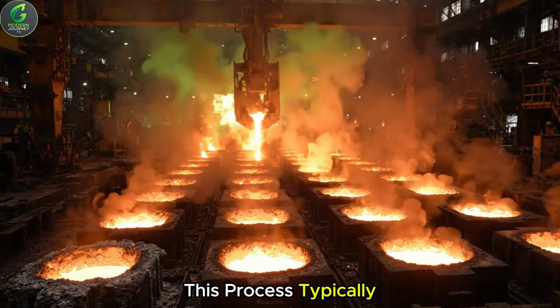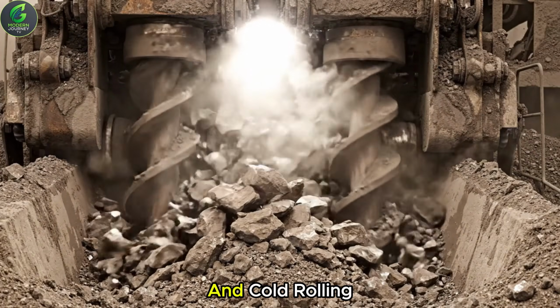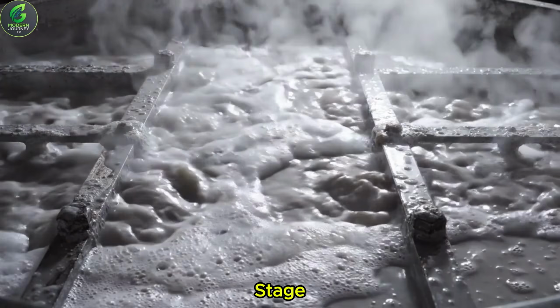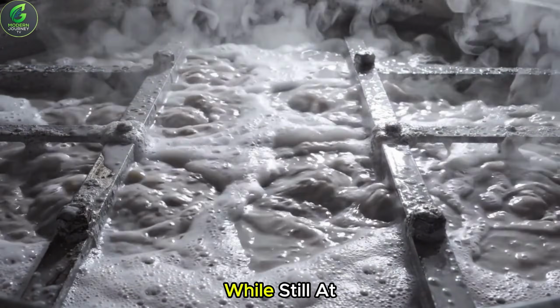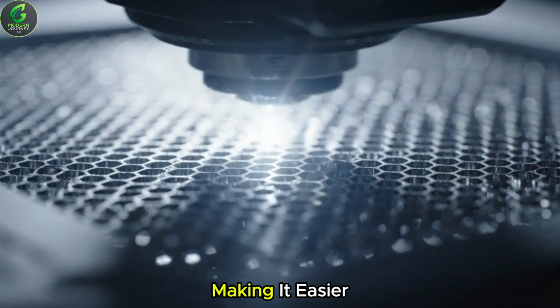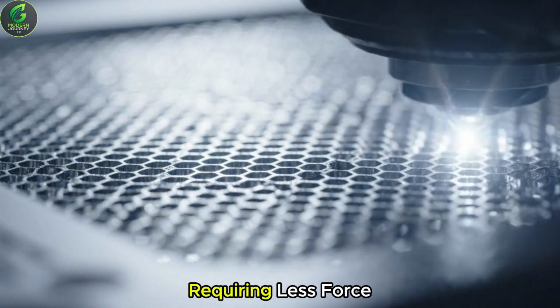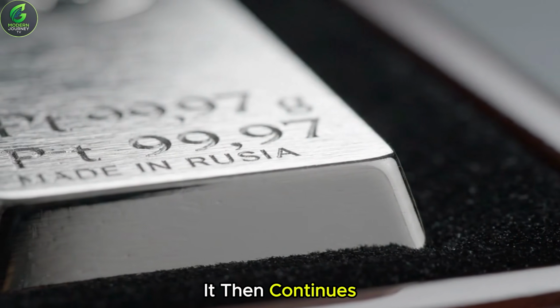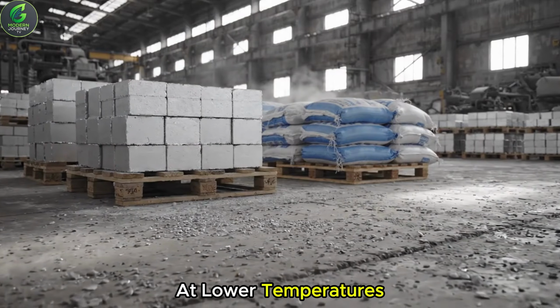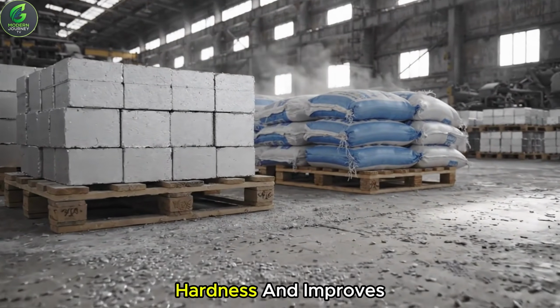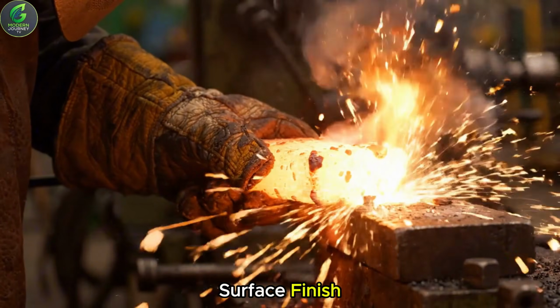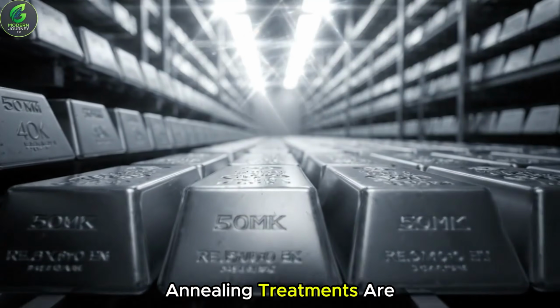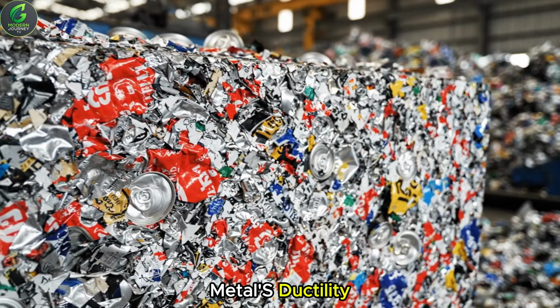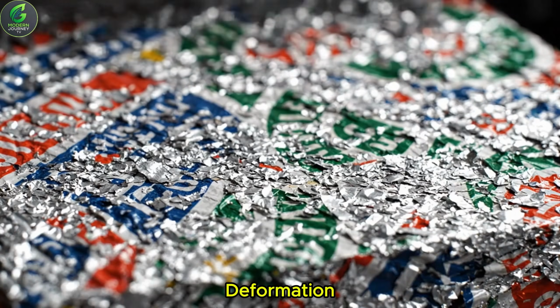This process typically combines both hot rolling and cold rolling. In the initial stage, aluminum is rolled while still at high temperature, making it easier to deform and requiring less force. It then continues through cold rolling at lower temperatures, which increases strength, hardness, and improves surface finish. Between rolling cycles, annealing treatments are applied to restore the metal's ductility after it has hardened due to deformation.